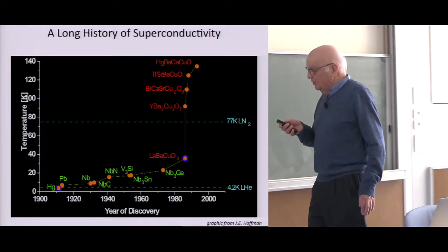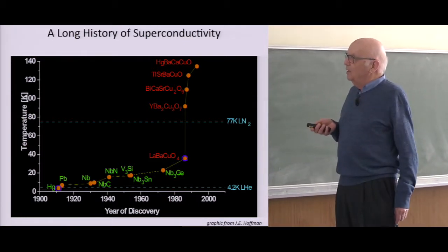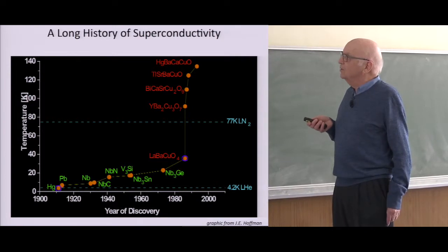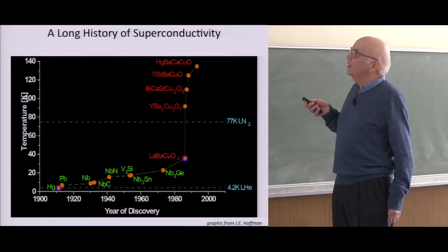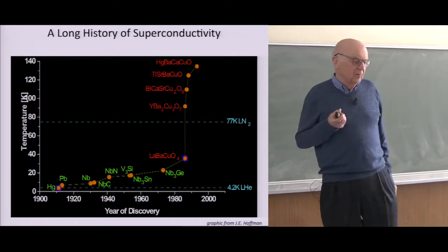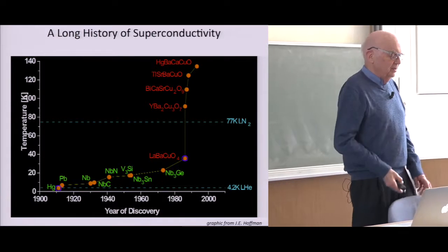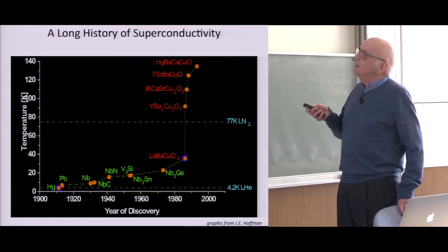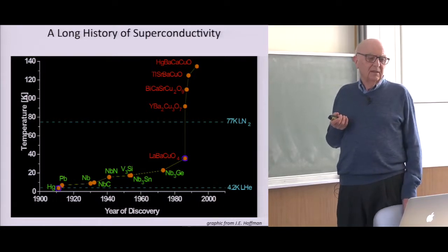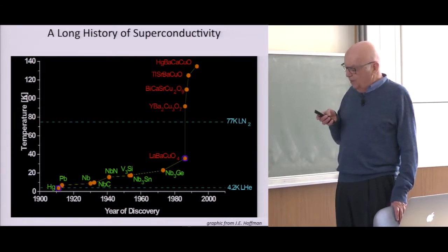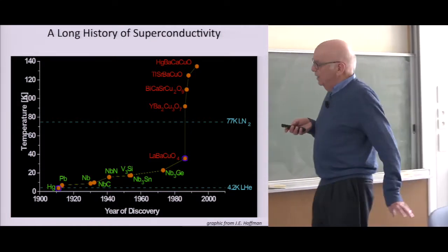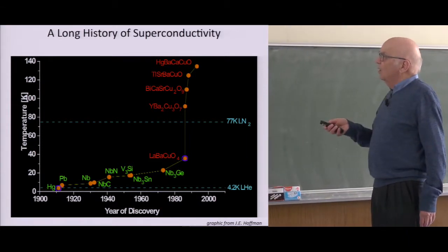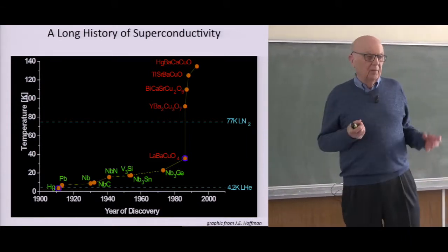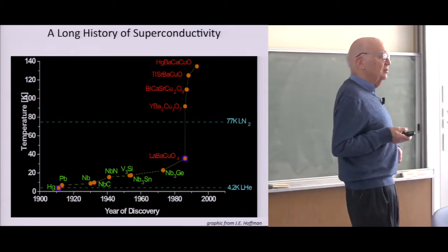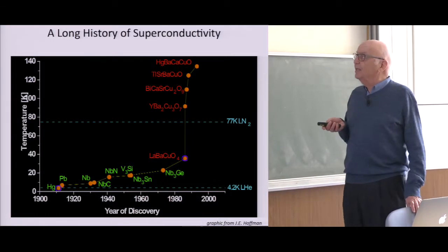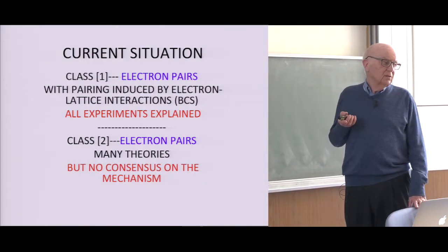And so what happened was, after that, people wanted to raise the transition temperature, but it went up 1 degree every 3 years, a third of a degree a year, until the 1980s when it shot way up, with copper oxide systems. And the highest temperature for the last 15 years has been this material, around 165 K, with some pressure. And then other materials came in. So the point was that up to this point, almost all of these superconductors are explainable by electron-lattice interactions, class 1 superconductors. And for the other ones, everybody has a theory, but there's no consensus.